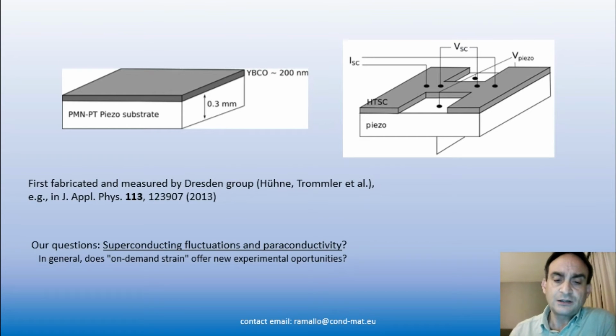These systems are like in these representations. You start with a substrate of a piezoelectric substance. For instance, typical is PMN-PT that you can find commercially in single crystals, and you grow on top of it a high Tc superconductor like, for instance, YBCO. Then you make some lithography in the superconductor so as to be able to apply certain electrical contacts. And there are two types of contacts. You apply a transversal voltage and you apply a longitudinal voltage. The transversal voltage you apply to the piezoelectric so as to change the size of the material on demand just by changing this voltage. So that produces a strain on the superconductor that it inherits because it is grown on top of it.